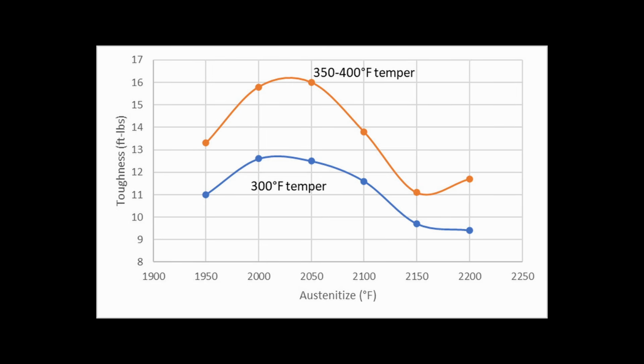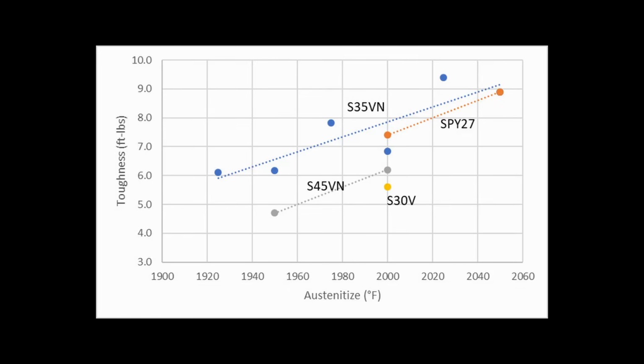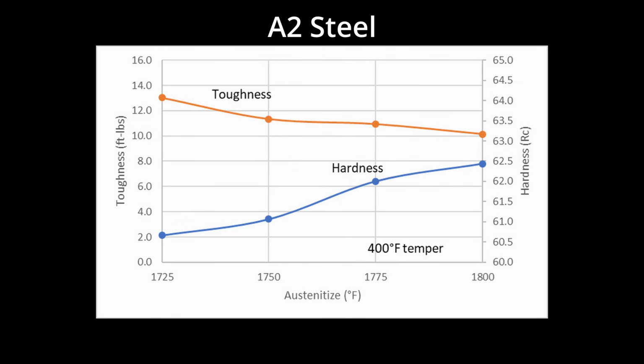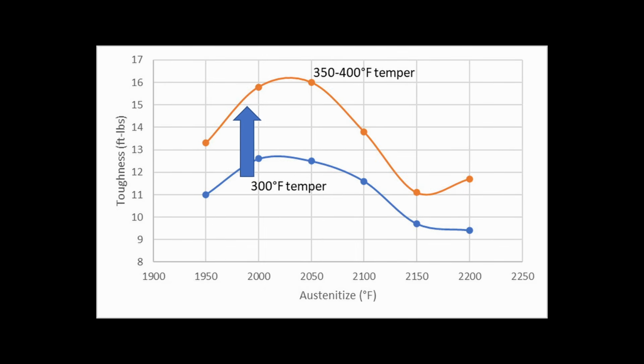This is somewhat counterintuitive, as generally reduced hardness leads to improved toughness, but I have seen similar behavior in some other steels including S35VN, S30V, and S45VN. During the austenitize, you dissolve some amount of carbide. Those carbides are beneficial to wear resistance and detrimental to toughness. In general, the increased hardness washes out any effect of decreasing carbide by going higher in temperature. But in the case of these steels, there is a crossover point where going lower in temperature means more carbide and therefore lower toughness.